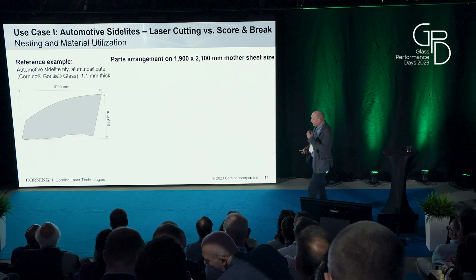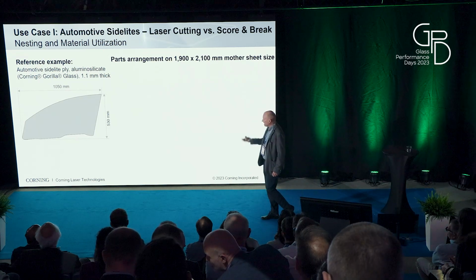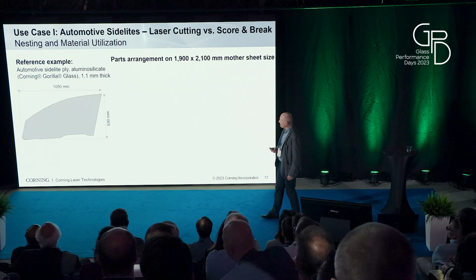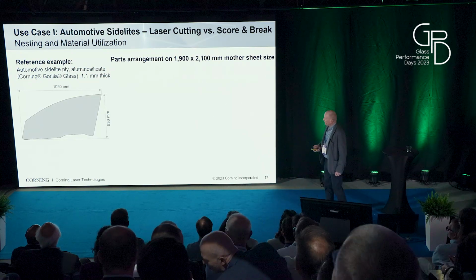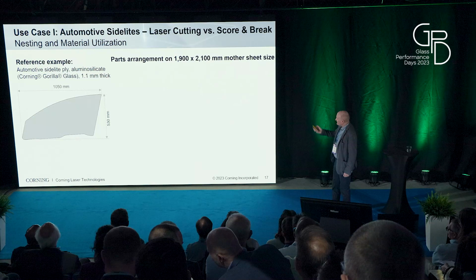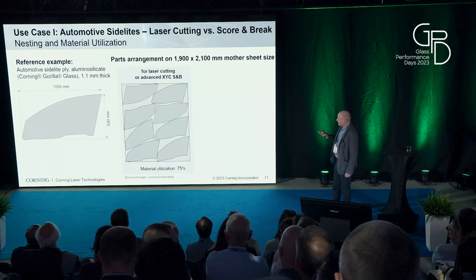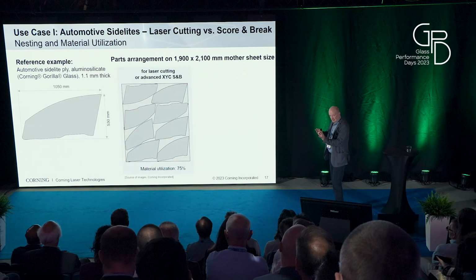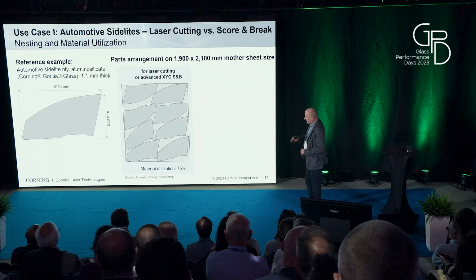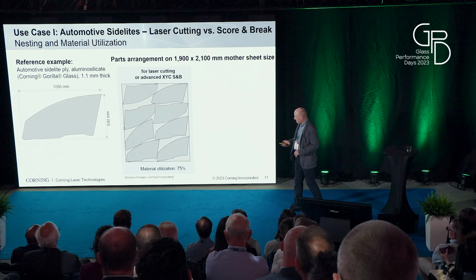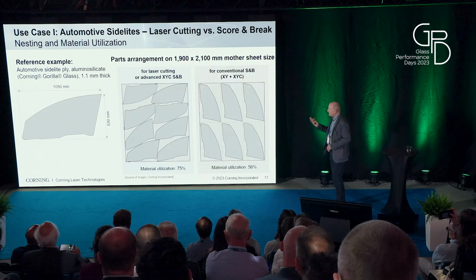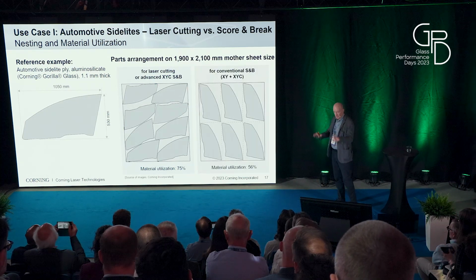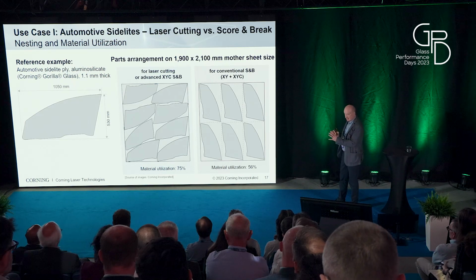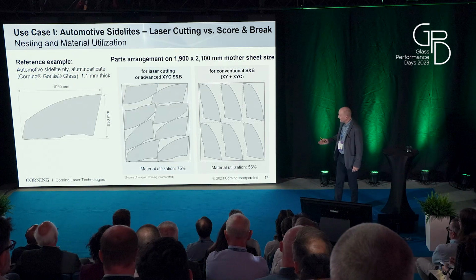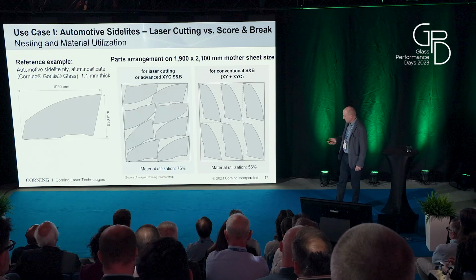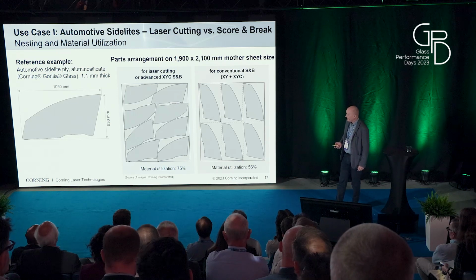Now here the use case, this is a drawing of a sidelite. It's a little bit distorted, generalized drawing. Here done with Gorilla Glass, 1.1 millimeter thick. And on this given mother sheet size, when we do the cutting with laser, we can tightly nest those freeform designs so that we get 8 parts out of a mother sheet with a high material utilization. If it is done with conventional score and break, where they cut first the rectangles and then the near net shape with the XYC cutter, you get only 6 parts out of such a mother sheet with a lower material utilization.